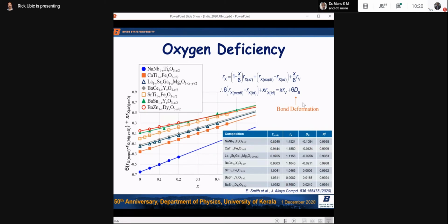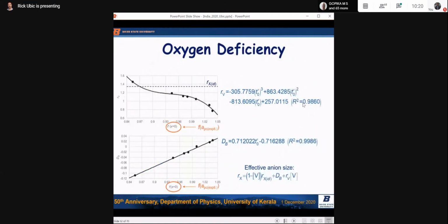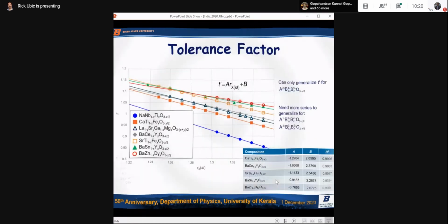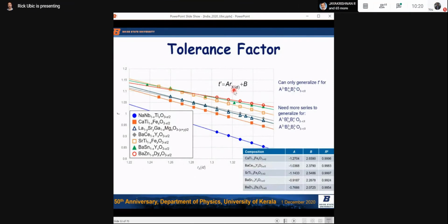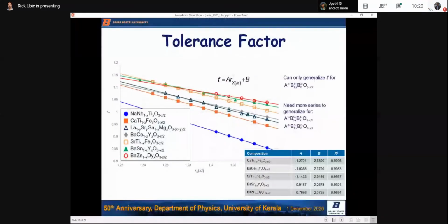Now we need to generalize this. So again, we've generalized it. This is vacancy size. This is bond deformation. We've graphed these as a function of t prime when s equals 0. Let me just remind you. And off we go to the races. And we have, remember, t prime is a function of the x ideal. And these guys, these are just a line, right? These are our lines. T prime versus x ideal, right? So these are all lines. This describes the lines. We need the AB coefficients. Here are the AB coefficients.